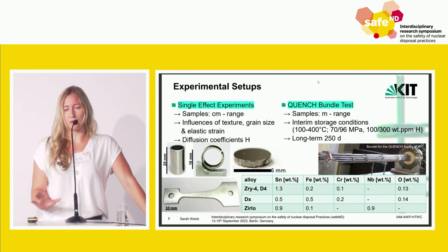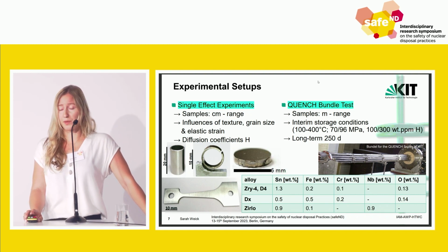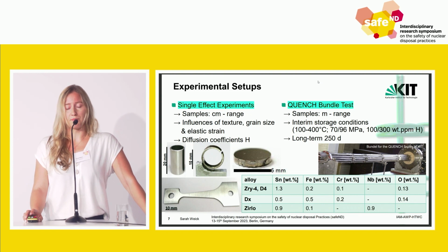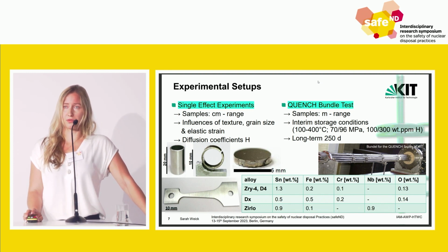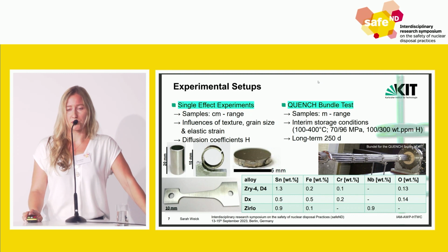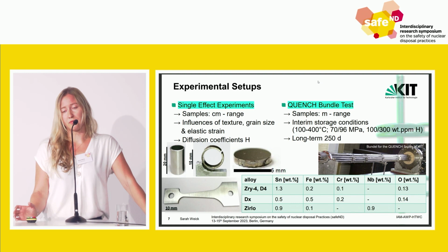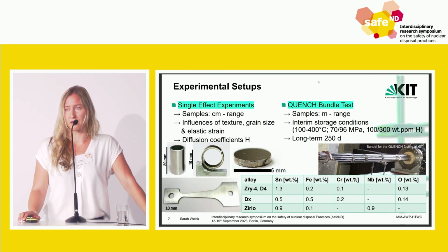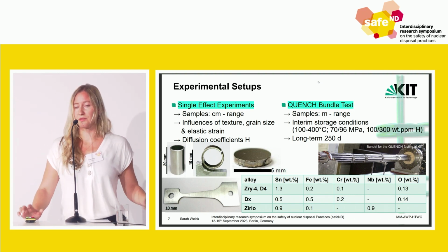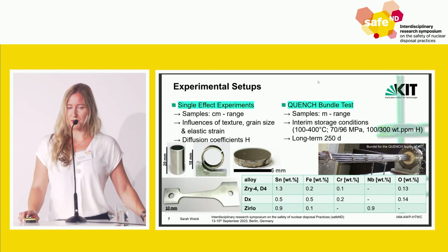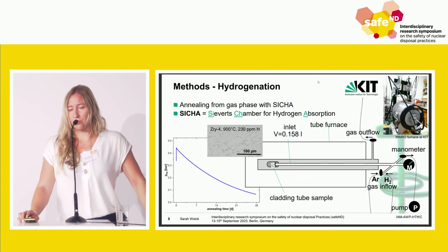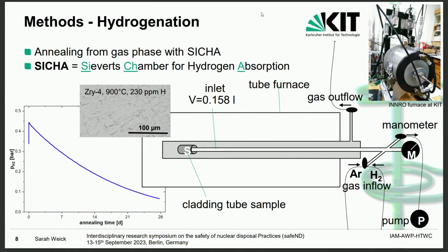So these are the materials that we use in general, and then at the quench bundle test we try to simulate interim dry storage conditions. We simulate the same temperature conditions, starting with 400 degrees at the central rod, and we try to have 2 different pressure conditions, 2 different hydrogen concentrations, and several different kinds of setups. So before we start with our experiments, we need to hydrogenate our samples.